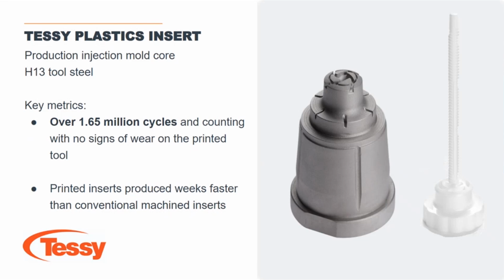Some of them actually wanted to put it to the test, where Tessy here has been running 2 different Mantle inserts in a 32 cavity tool for over 1.65 million cycles with no signs of unexpected wear. This is actually a deodorant component, so it's really, really high volume. And they also were still able to print the inserts and do the finishing involved weeks faster than conventionally. And this insert's still running, this number 1.65. We have to update every month or so, but this is just our great gold standard of durability of the material to show that it is an equivalent material to the tool steels that you're using today.